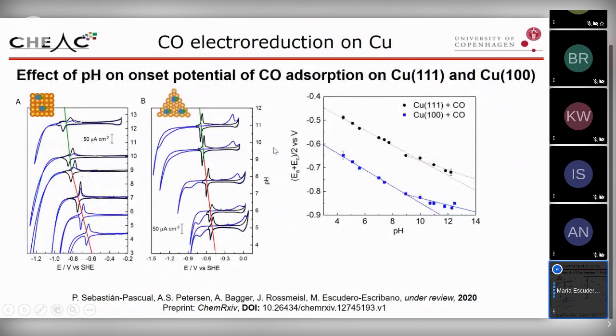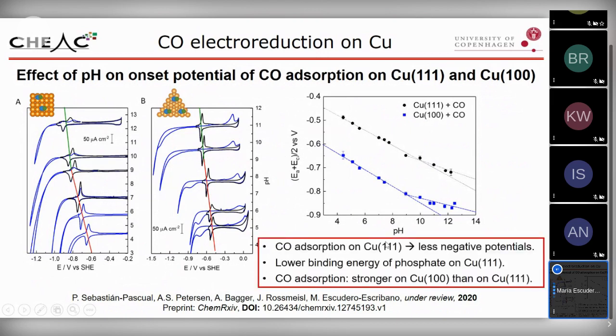So we can see it better here, and this is just the average between the anodic peak and the cathodic peak versus the pH. So we see how the pH influences the CO adsorption features. We can compare copper 111 and copper 100. The CO adsorption on copper 111 occurs at less negative potentials, and this is an indication that on copper 111 the phosphate has a lower binding energy, and that the CO adsorption is stronger on copper 100 than on copper 111.